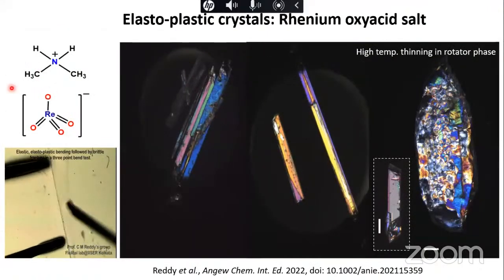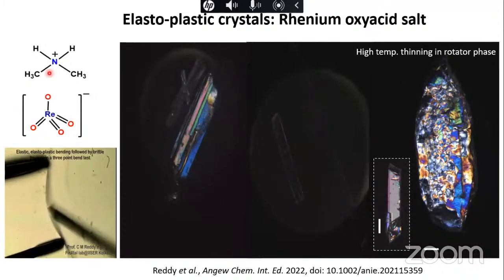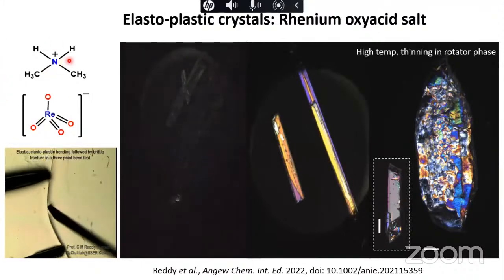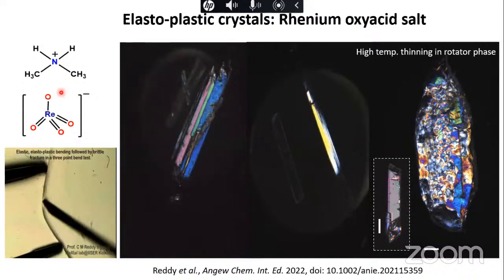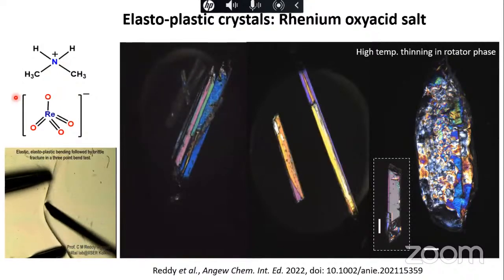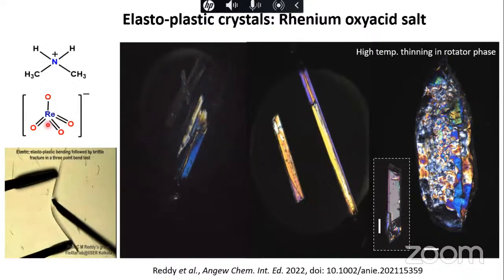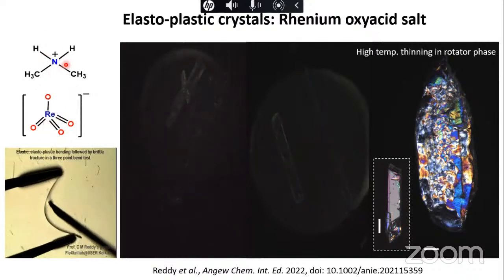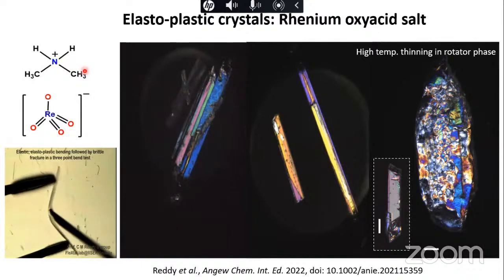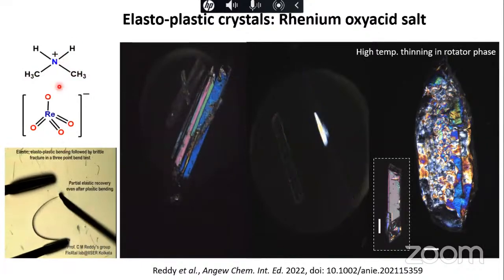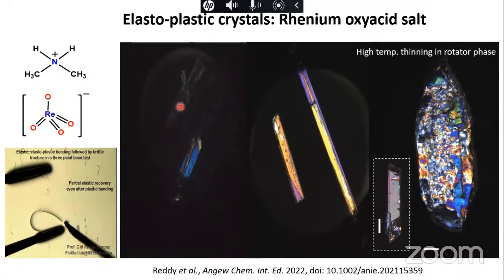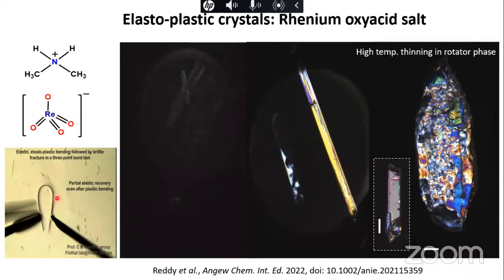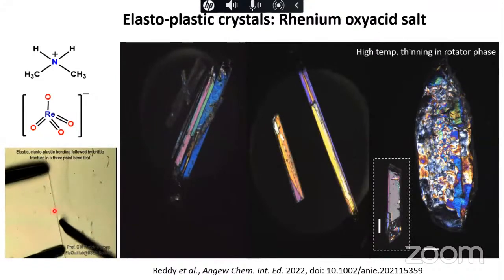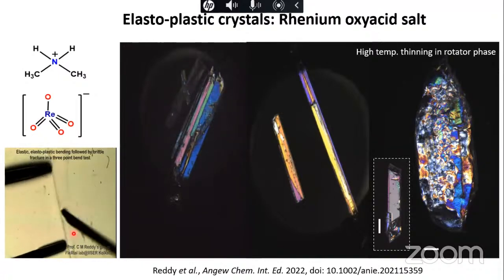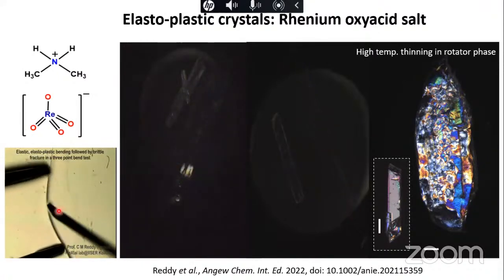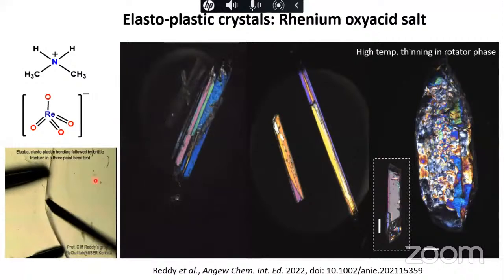Then we were obviously interested in the mechanical properties, as well as the plastic crystalline nature, where you have dynamic disorder. So we looked at this particular example. This is a rhenium salt with an ammonium type of ion. When we form this salt, we found that these crystals can elastically bend, and beyond a point they also become plastic. That means initially they are elastic, and if you push further, you have plastic deformation.